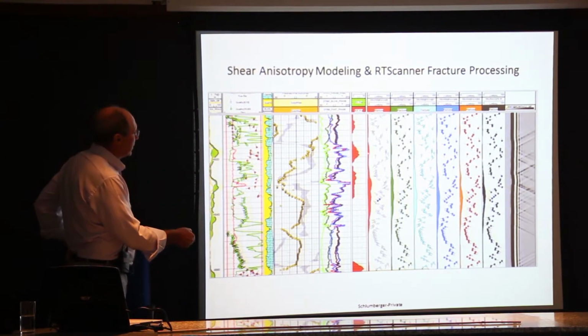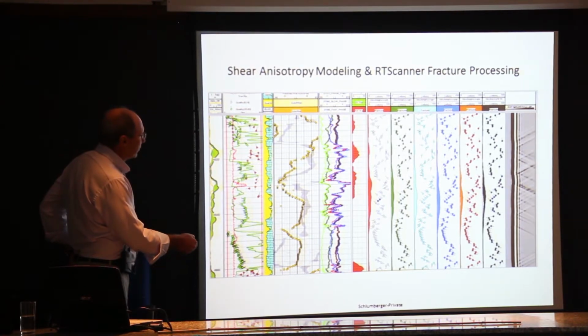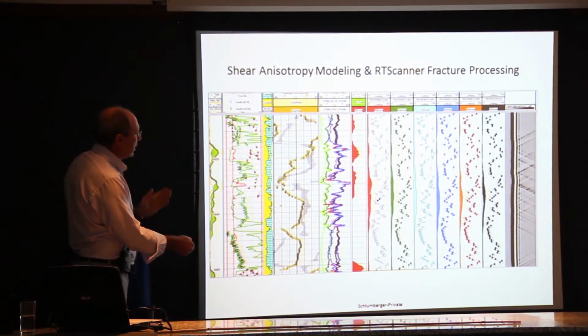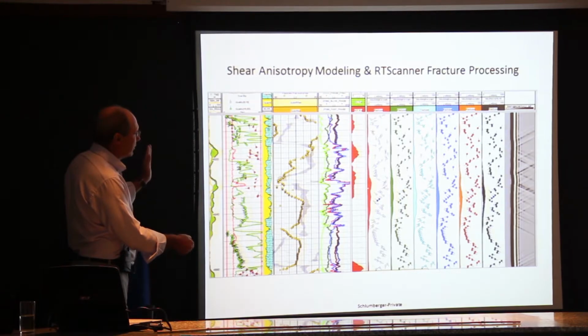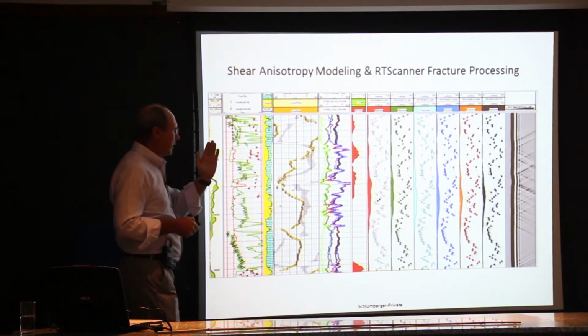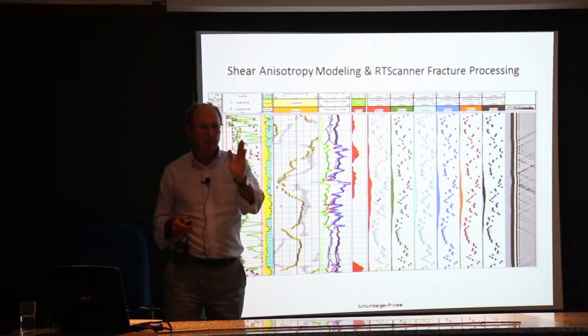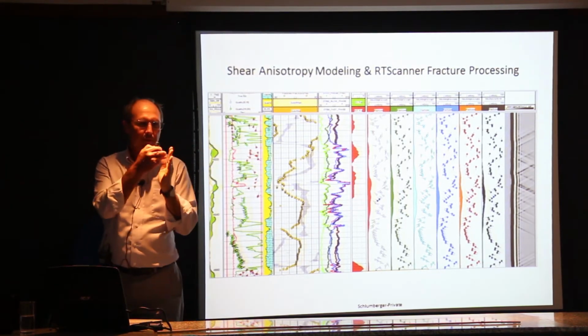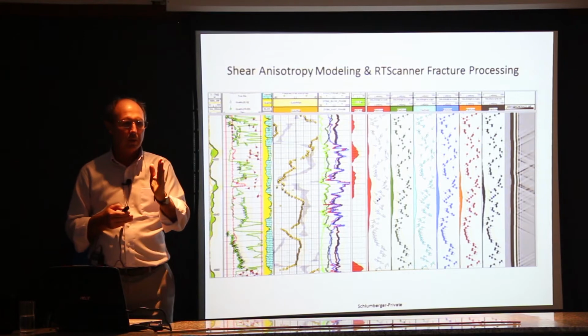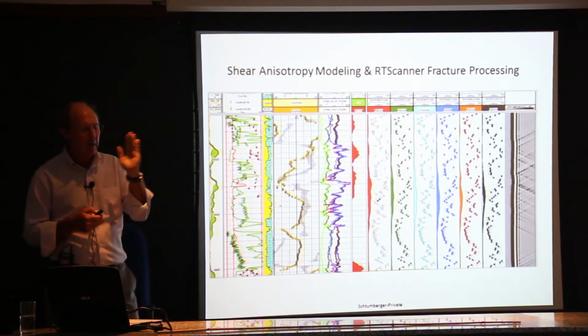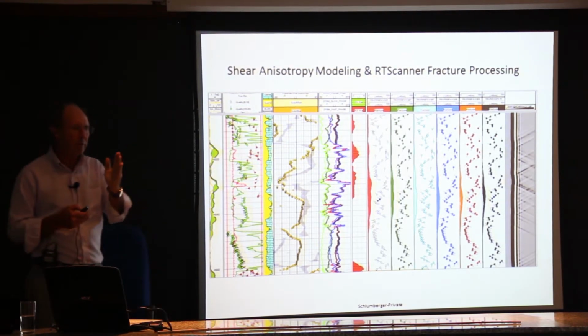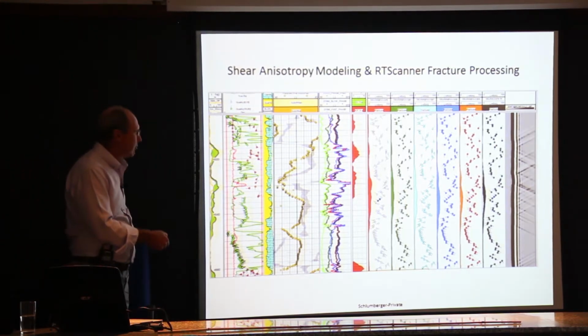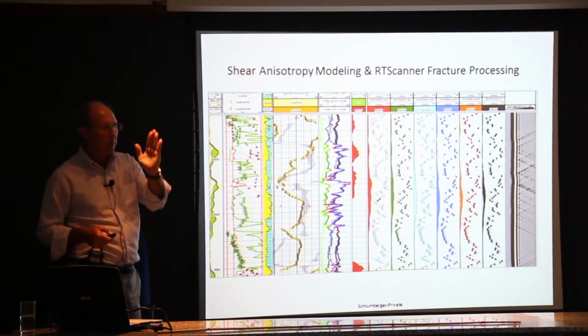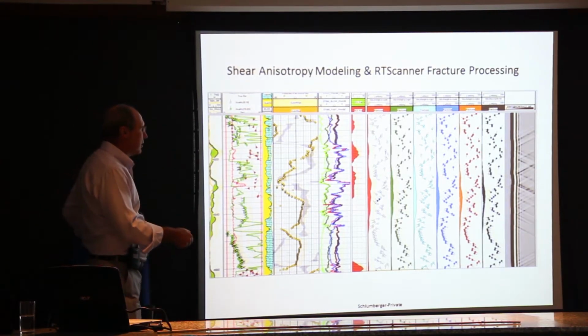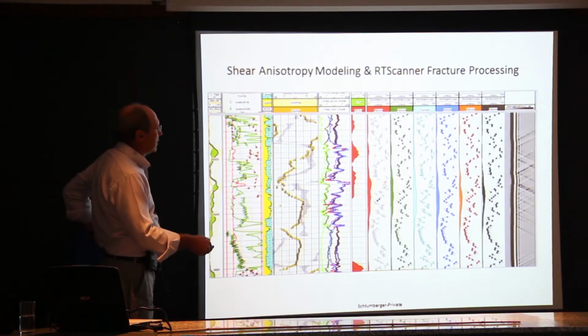And what this is here is basically the difference between the inline and the offline rotated resistivities. So the inline resistivity is now aligned with the fractures, and the fractures are filling up with the oil-based mud filtrate, which is high resistivity. So this difference in resistivity, and you can see it's consistent as you go deeper into the formation. This is an indication these would be natural fractures.